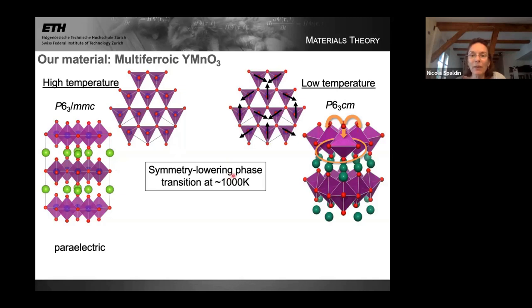The first thing is that the trigonal bipyramids tilt. So this oxygen on the top of this trigonal bipyramid will tilt downwards and inwards, and this one tilts downwards and to the left, and this one tilts downwards and up. So they make these groups of three; they trimerize in this threefold tilting. And the next ones here also tilt like this. I've tried to sketch this here by showing these arrows showing the tilting of these trigonal bipyramids. That's the first thing that happens, and that lowers the symmetry to a polar space group, P63cm.